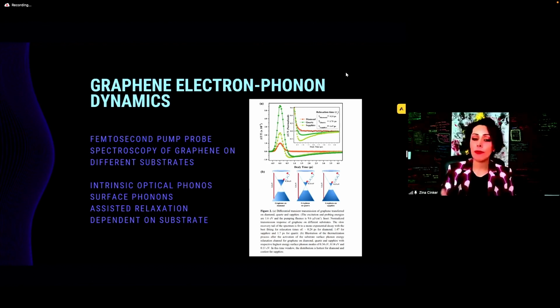What we've discovered is that there are interactions with the substrate, not only through the assistance of regular and conventional phonons, but there are surface phonons and intrinsic optical phonons within graphene. All of that, what does that mean? That means that the graphene electronic dynamics can actually be tuned based on the substrate that it's sitting on.